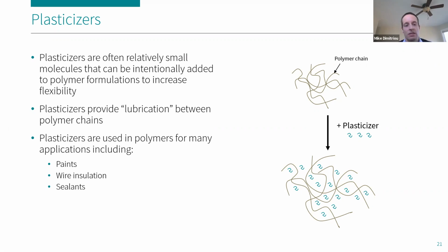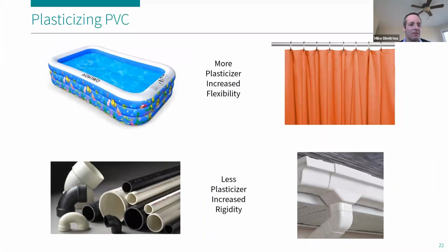And this is not a novel concept or technology. Plasticizers have been around for a very long time, and they're typically used in most applications in construction. Examples might be paint, wire insulation, and sealants. So to highlight the effects of plasticizer, an easy example is polyvinyl chloride, or PVC. What you can see at the top is one form of PVC where plasticizer, or at least more plasticizer, has been added. And you can get things like shower curtains or inflatable pools, where these materials have an increased amount of flexibility. On the flip side, if you remove plasticizer and only have that PVC, or have a reduced amount of plasticizer, you get a material that's significantly more rigid and stiff, like piping and gutters.